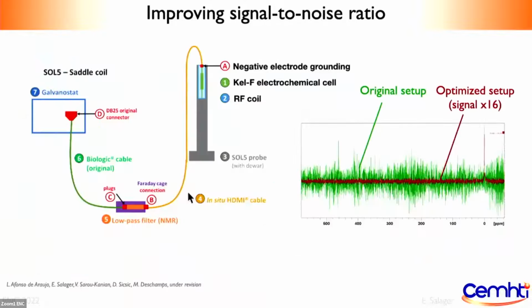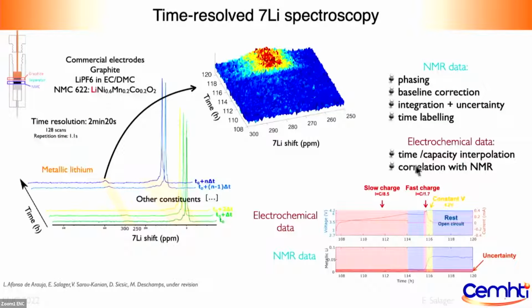And so this time we get a lot of noise from this setup, and this has been sorted. You need to ground your negative electrode. You need to protect. We put a Faraday cage around our unshielded connections, and we could reduce the noise so that you actually can see the lithium signal you're interested in. And so with this, we can start doing our time-resolved lithium spectroscopy. So we record one spectrum as we charge and discharge the battery, and we observe the metallic lithium region.